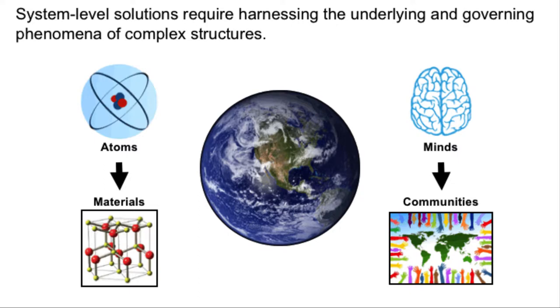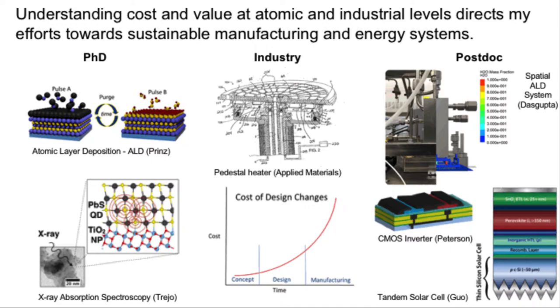And that's something that, at least through the professional experience I've had in academia, I've come to understand a little bit more. At the PhD level, working with Fritz Prinz, thinking about atomic layer deposition, both its value, but also its cost. Its value in the sense that you do have that tunability, that control of atomic structure, but the cost in the sense that it's very difficult to understand what you're making. Yeah, it's difficult to characterize what you're making. It's actually a very slow process. So when we're thinking about scalability, ALD by itself doesn't make sense in the big picture.